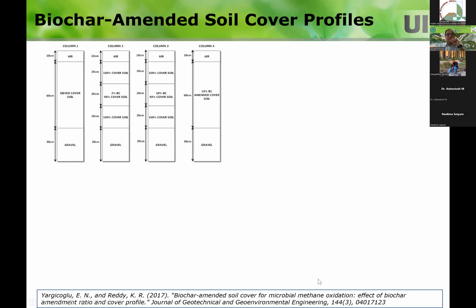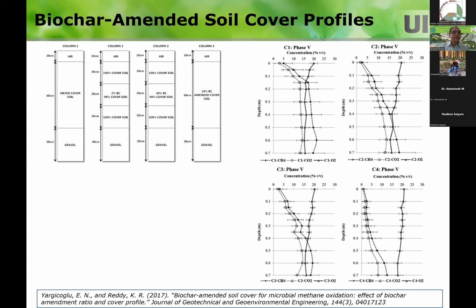So then, we said, okay, we're getting good results. Can we optimize the design, optimize the content? So we have a control with just the soil, and we looked at, okay, instead of putting the entire soil with the biochar amendment, can we reduce it? Because the more biochar you use, it's going to be more expensive, more tedious. So we said 2% biochar here, and 10% biochar here. We don't need it across the entire cover, maybe some zone where we expect the maximum methane oxidation. So maybe we can put it in that. And in one case, we put 10% amended soil in the entire profile.